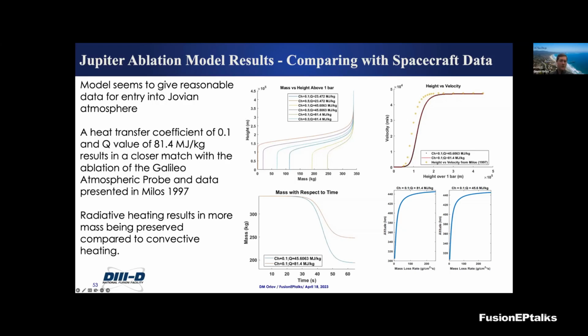He found that the models seem to give reasonable data for the Jovian atmosphere entries. The best result he got was with a Q value of 81 megajoules per kilogram and a heat transfer coefficient of 0.1. This was probably matching the Galileo atmospheric probe entry data the best.